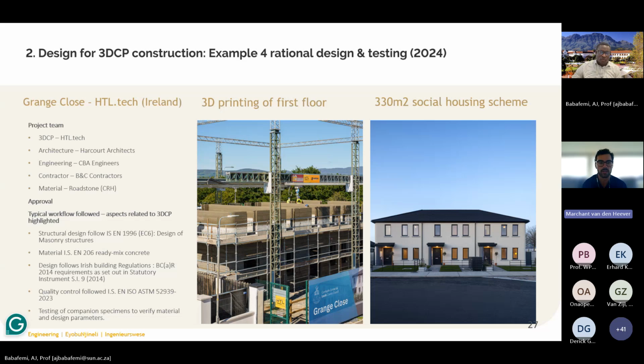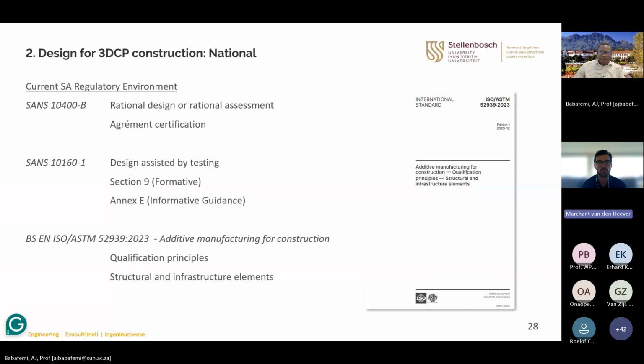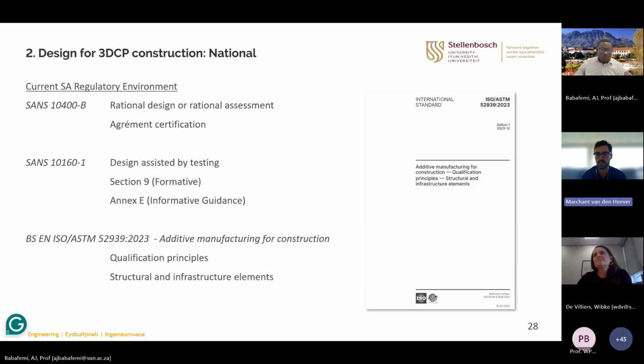So the materials were regulated according to EN 206. And then the Building Control Amendment Regulations, or BCAR requirements from 2014, according to the Irish building regulations, were adopted. And the quality control followed ISO/ASTM 52939 guidelines, as I covered previously. And then we conducted a series of companion specimens to verify that the material and design parameters were indeed executed correctly. So I think that's a nice overview of the various ways that we can regulate 3D printed construction. And I'd be happy to touch on some of these aspects in the Q&A after.